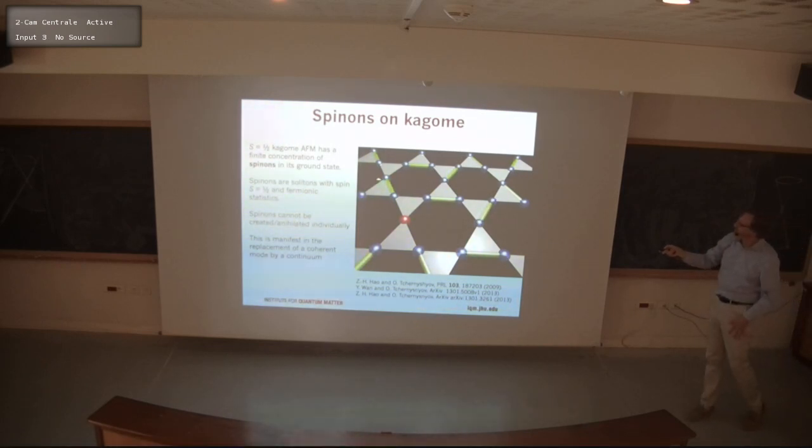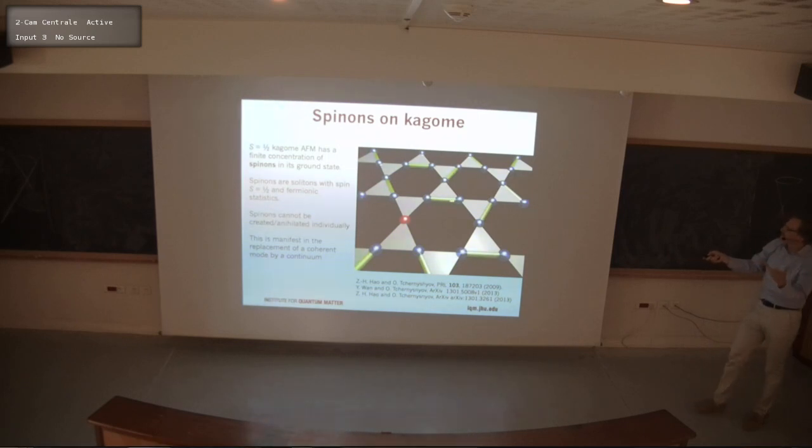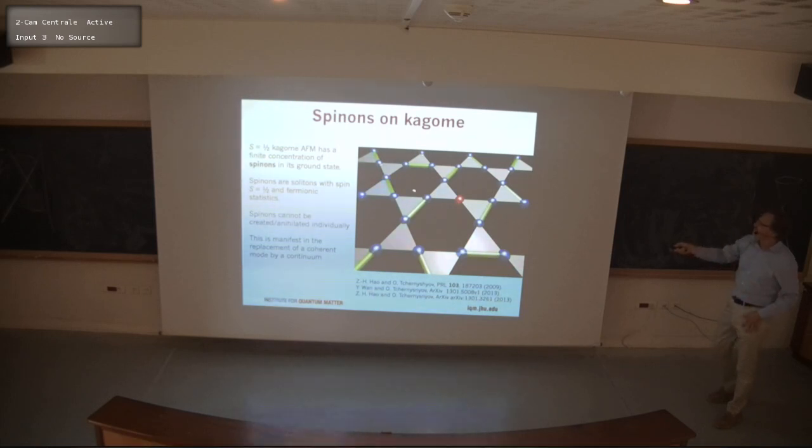So every spin is part of forming a singlet, except for some sites which have a spinon-type quasi-particle which can move through this quantum superposition as an individual particle. And so now the magnetic excitation I could do with neutrons would be to create a pair of such spinon-type excitations, and then they can move apart. That would give me my continuum, and breaking the singlet would give me my momentum dependence.